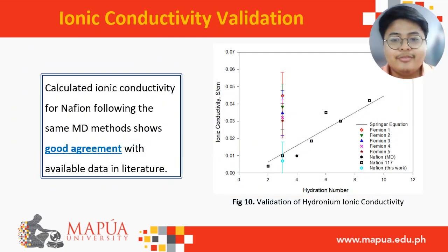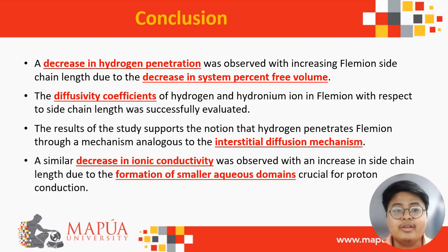For validation, we also applied our methodology to Nafion, and we found that the calculated ionic conductivity for Nafion, following the same molecular dynamics methods, shows good agreement with available data in the literature. This suggests that the methodology used for calculating the ionic conductivity in Flemion follows that of those for Nafion. All in all, we have determined that a decrease in hydrogen penetration was observed with increasing Flemion side chain length due to the decrease in system percent free volume.